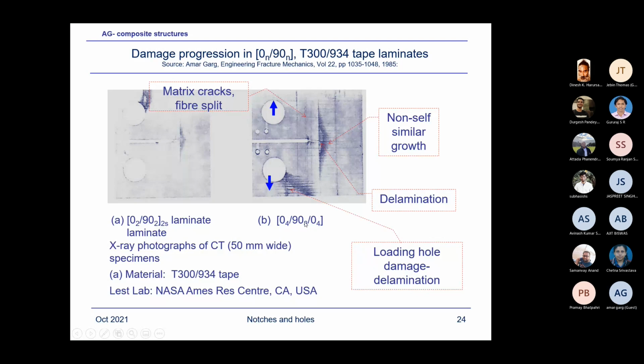And I was talking about interlaminar stresses, and this is due to the interlaminar stresses. Very high interlaminar stress will exist because you are clubbing or bunching of the 0-degree ply and 90-degree plies. So you'll create very high interlaminar stresses, which is causing the delamination, as you can see here. It's a true thing, and you can see the effect of high interlaminar stresses, bunching of the plies together. So it's a good phenomenon which is observed.